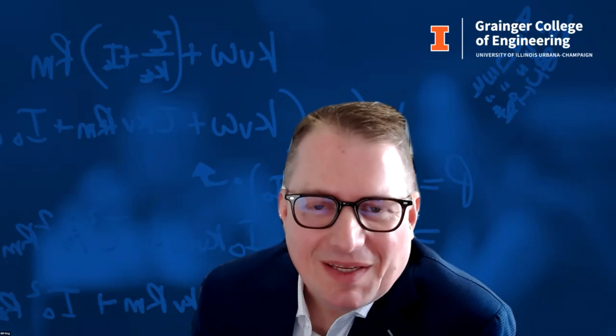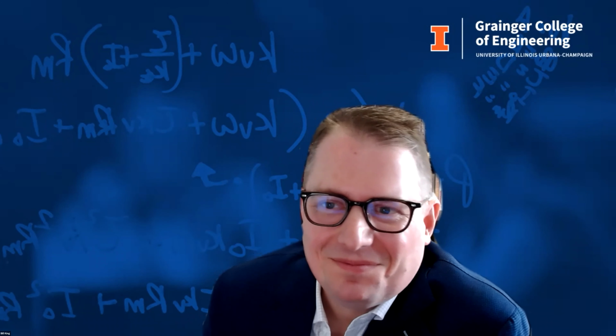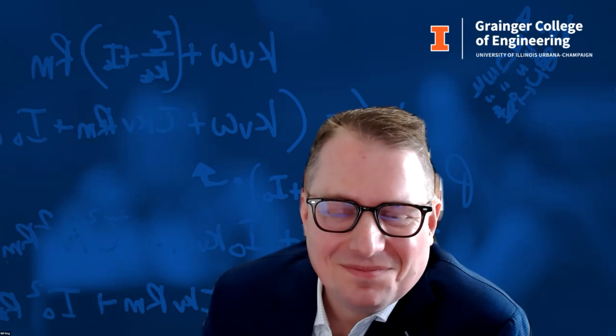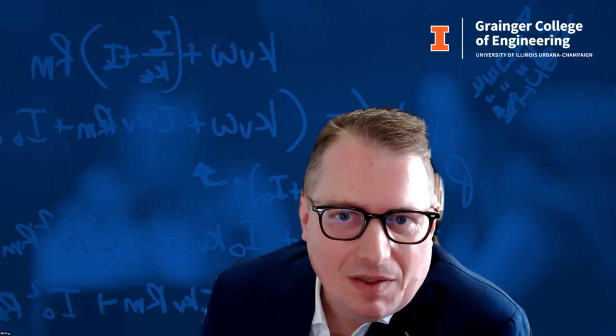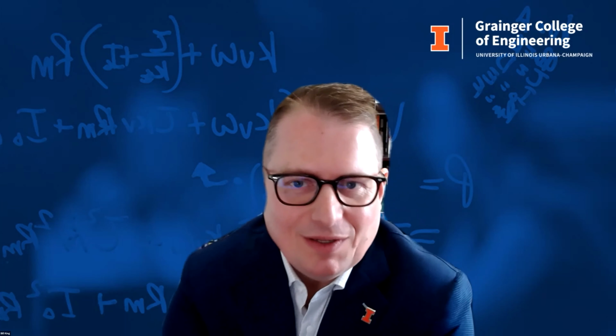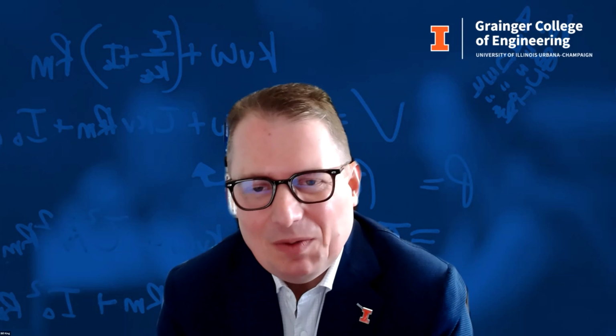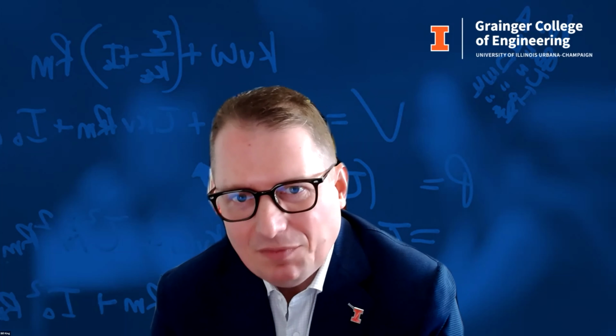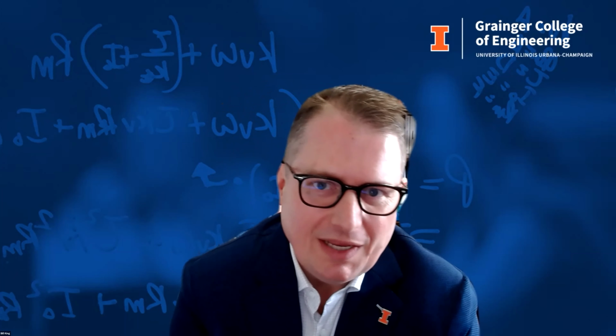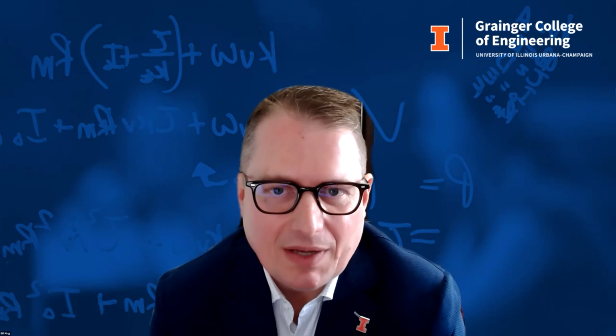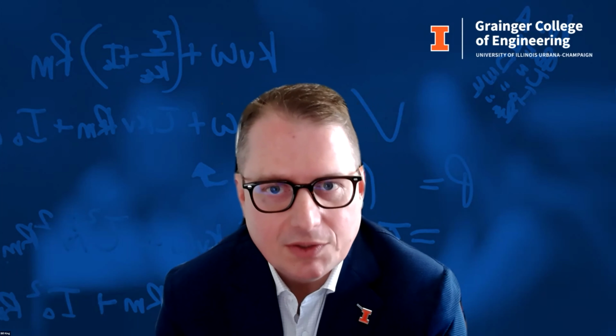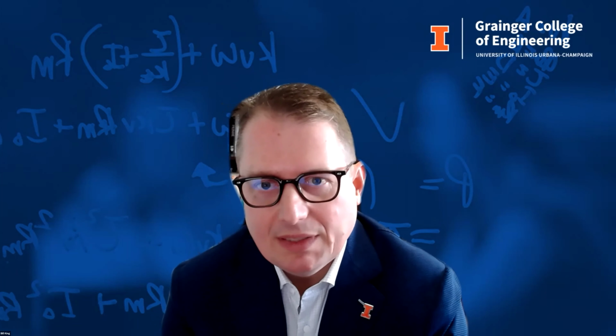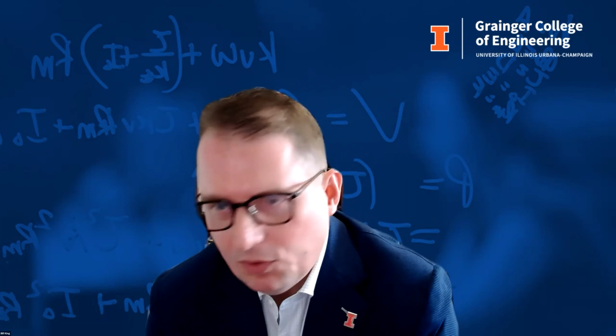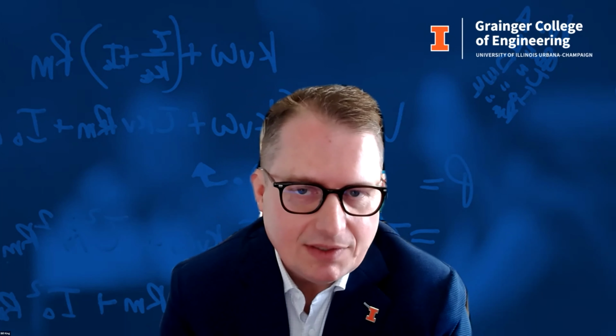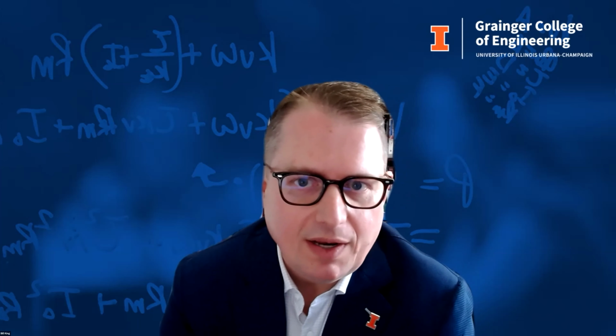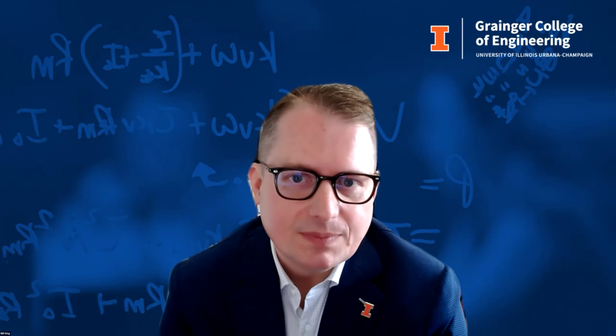Yes, absolutely, they can. I showed several. The powder-based processes for metal additive have really gotten a lot better over the last 5 years or so. Maybe in earlier days, the materials coming out of a commercial printer were more porous, and you had to be concerned about leakage issues. But with DMLS and other metal additive processes, you can now make a fully dense part that's watertight even with thin walls.